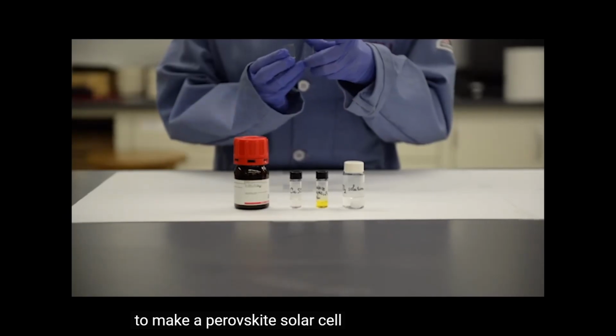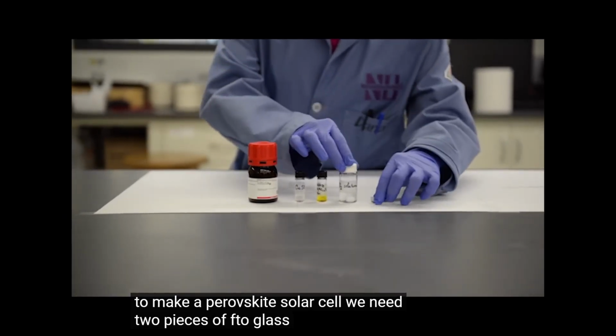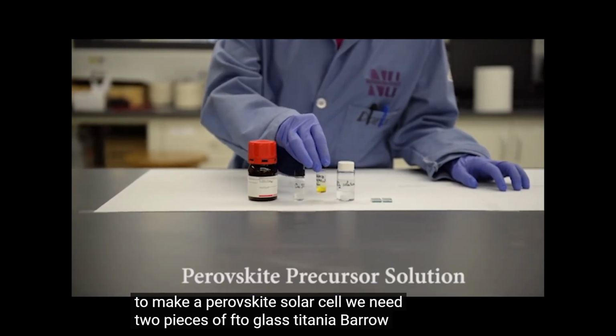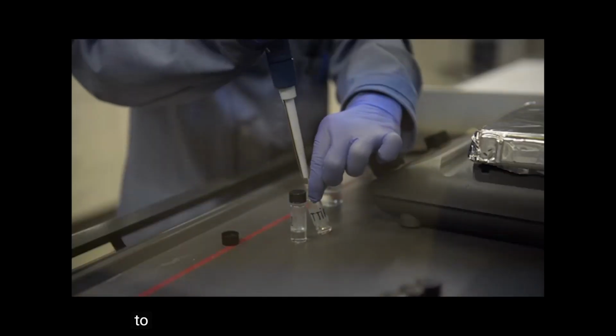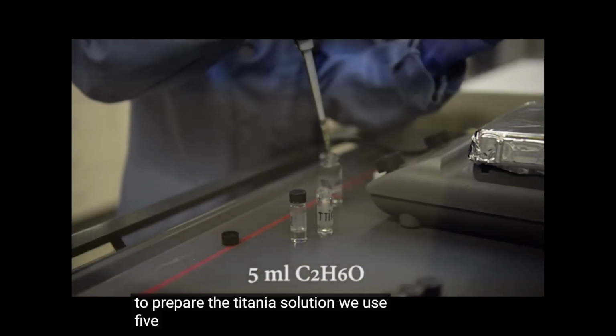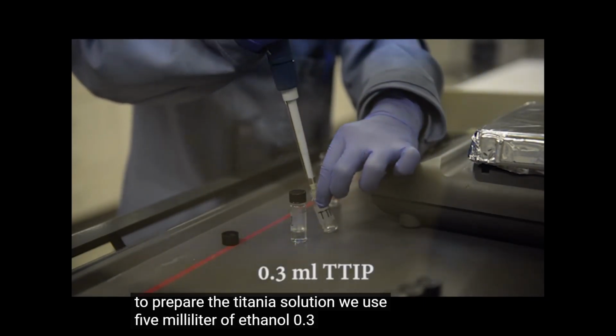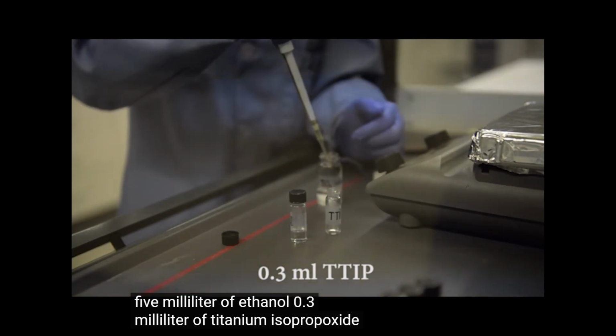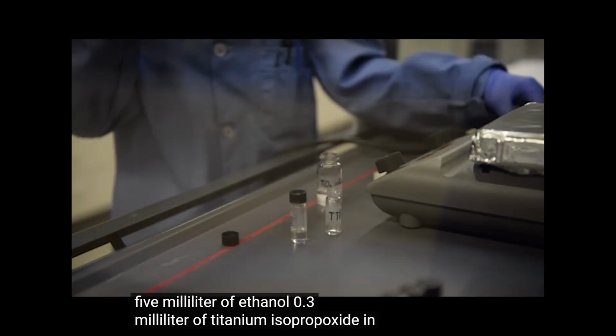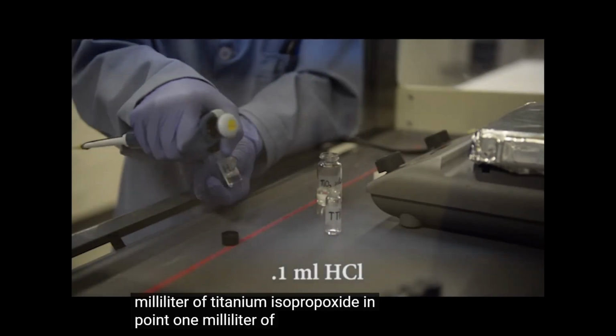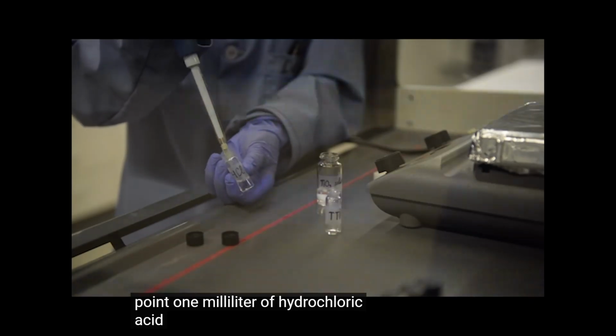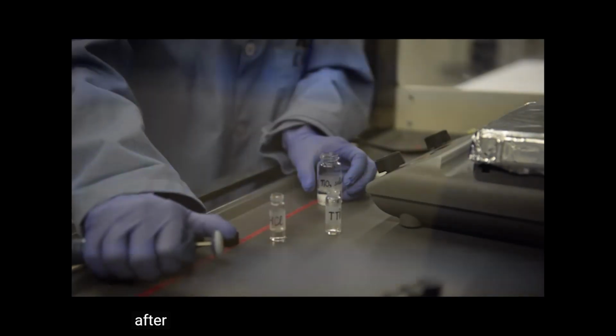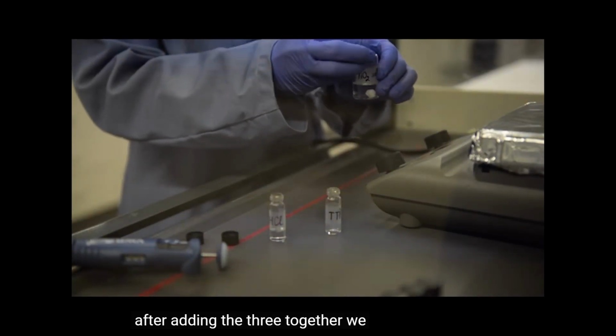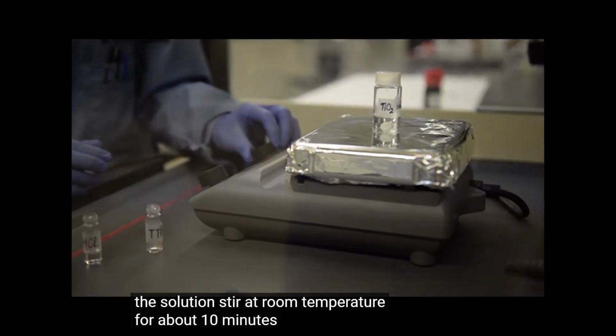To make a perovskite solar cell, we need two pieces of FTO glass, titanium, perovskite, copper thiocyanate solutions, and carbon powder. To prepare the titania solution, we use 5 ml of ethanol, 0.3 ml of titanium isopropoxide, and 0.1 milliliter of hydrochloric acid. After adding the three together, we let the solution stir at room temperature for about 10 minutes.